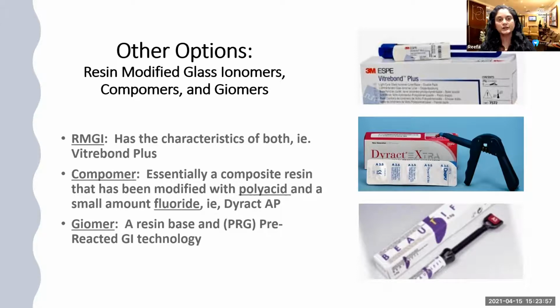Compomers have been around for a little while, and this is essentially a composite resin which has a little bit of fluoride in it. It has just minute traces of glass ionomer properties, primarily a little bit of fluoride. And then we have giomers, and these too have been around for a little while. This is a resin base and a pre-reacted glass ionomer technology. As far as the giomers go, they are not as strong as a resin modified glass ionomer. People do use them today. They're strong enough to be used in North America for posterior composites in primary dentition.